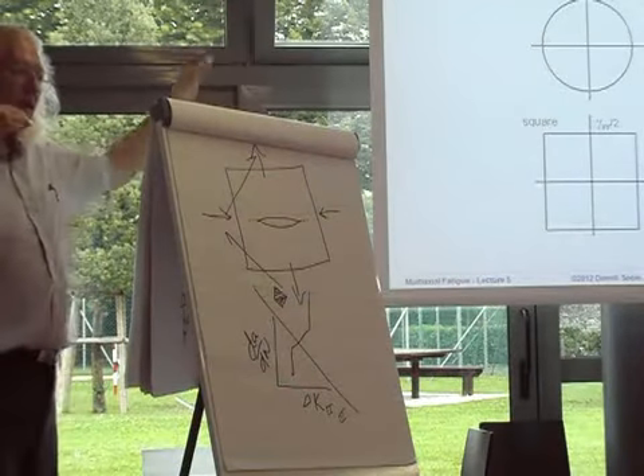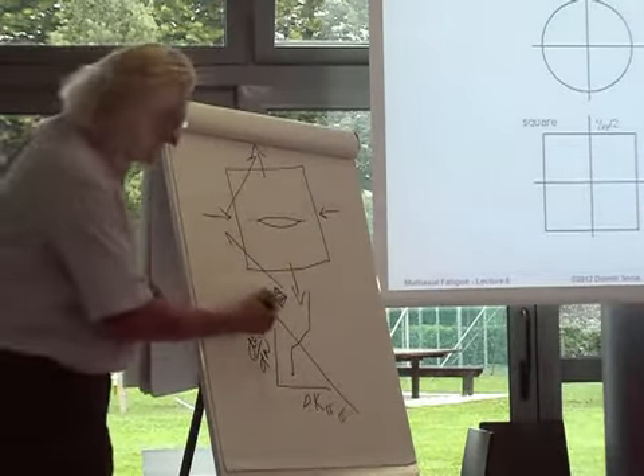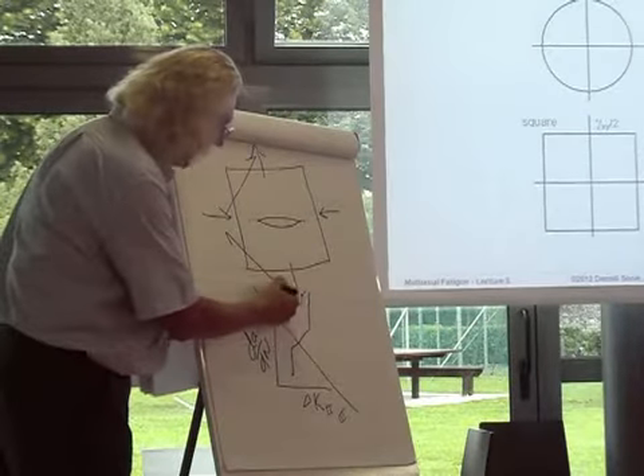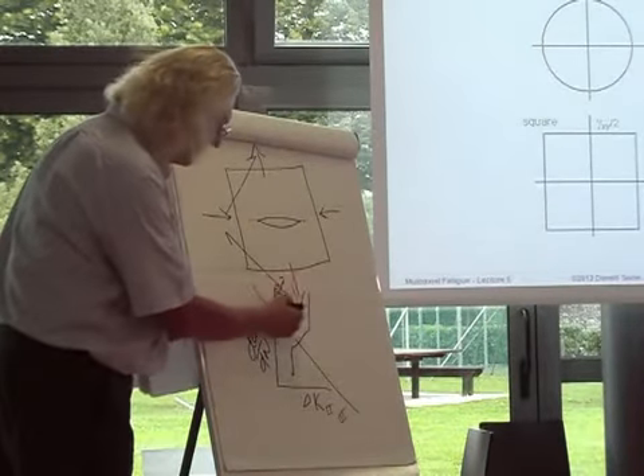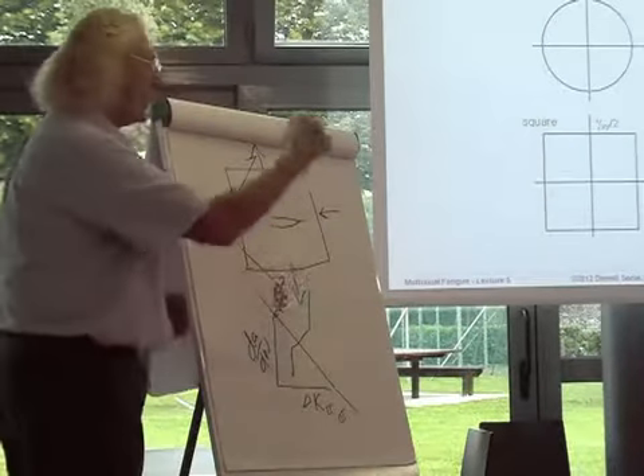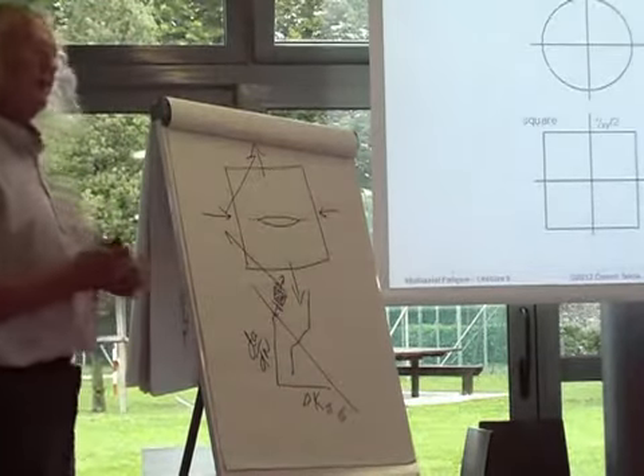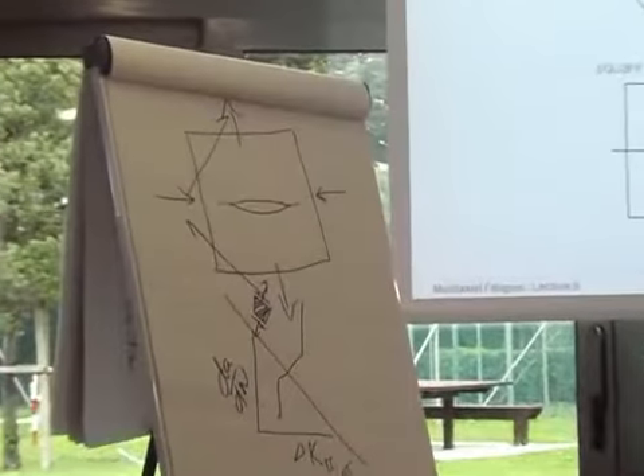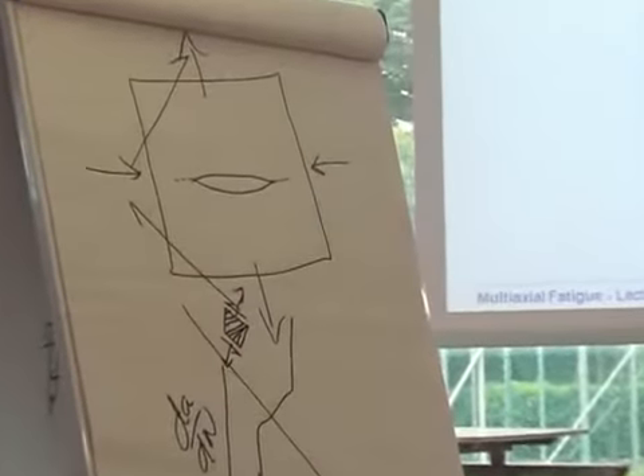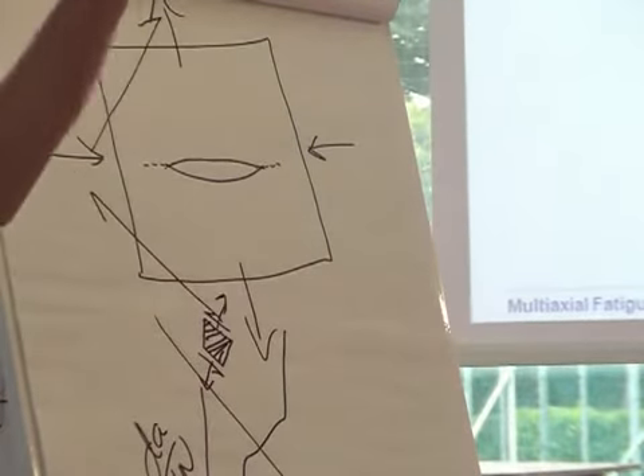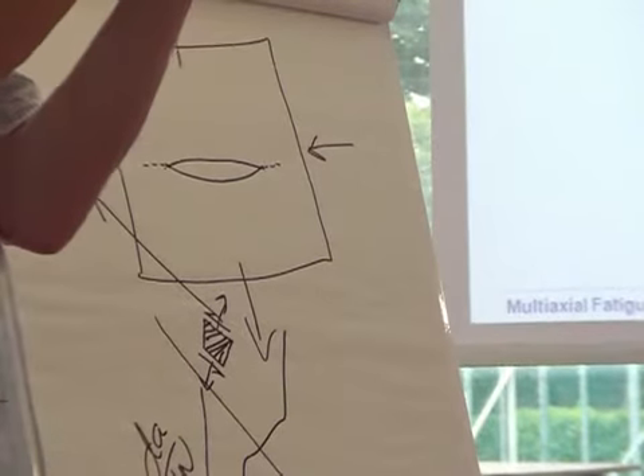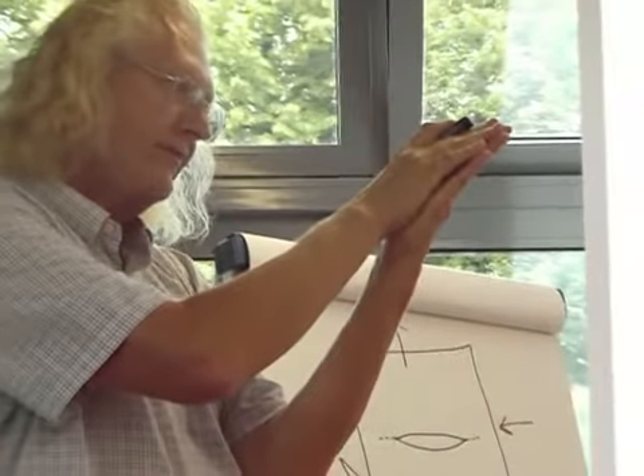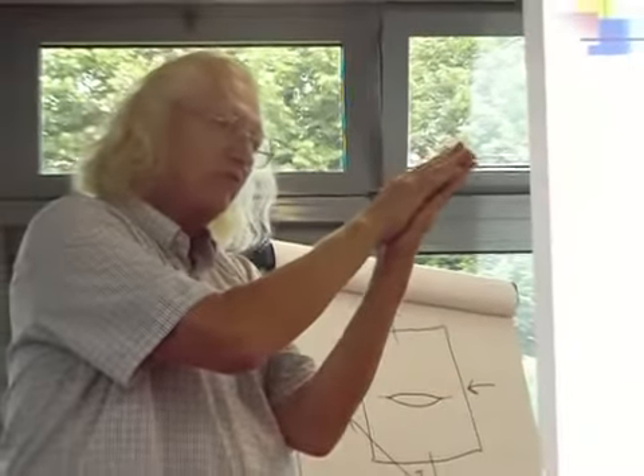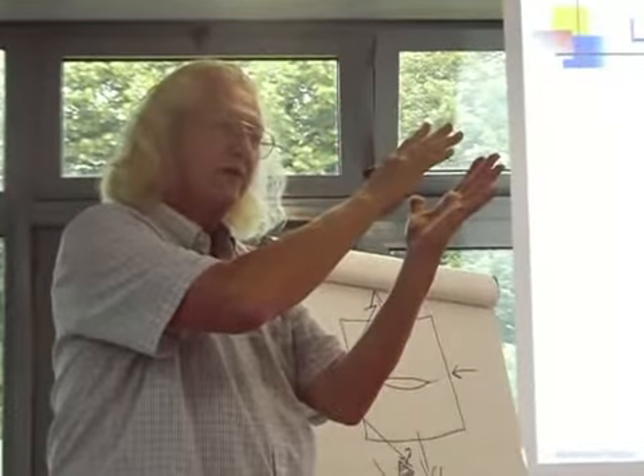Absolutely nothing. The only thing that this material knows is the stresses acting on it from whatever the source might be, and also the strain, right? From whatever the source might be. So I have no reason to believe that the fatigue mechanism would be different, because this material doesn't know. So we still have this idea of, okay, we have some shear stresses driving the nucleation and growth of these microcracks, and we also have these normal stresses which tend to open up the cracks.